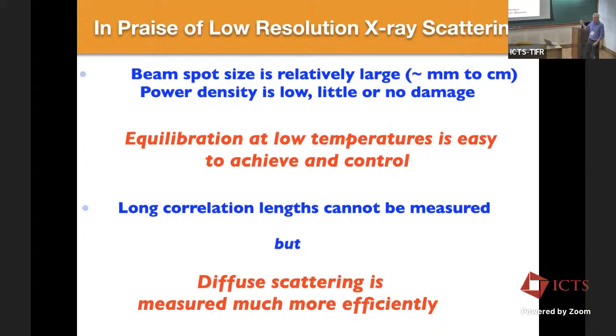Okay. Anyway, so I've been mentioning that we do these low-resolution X-ray scattering measurements. The way I think of them is that they're neutron scattering experiments, if you did them like a neutron scattering experiment. So the main difference is that the X-ray source that we use is a so-called rotating anode, and it's an incoherent source, which means that the X-rays are produced and go out, they don't quite go out in all directions, but they go out almost in all directions, okay?